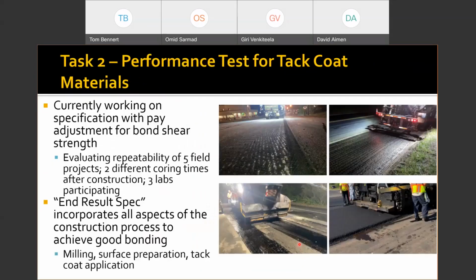But in the end, a lot of it also comes down to construction practices, how well we actually construct our pavements. There are a number of areas in these pictures where there's improvement to be made or errors that are involved. In the first picture here, you can see a milling practice. Now, what has to happen after this milling practice, again, where we're taking off 1.5 to 2 inches of old material? You can see old dust and debris fines that are on this road. This has to be removed. So we have to come in with a sweeper.